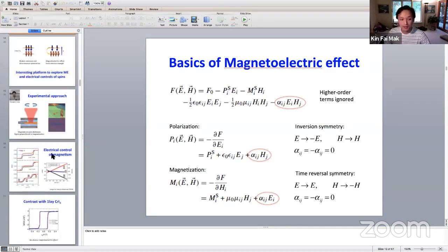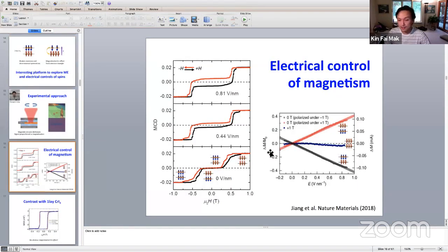What I'm saying here is whether there is a linear magnetoelectric effect happening. So at least for small electric field, there's no signature of a linear magnetoelectric effect. And maybe at a large electric field, you do see a little bit of deviation from zero, a non-zero change in the spin aligned case, but it's hard to say at this point because it's a nonlinear effect. Yeah, you are right that the electric field can break the inversion symmetry, but it's a nonlinear effect.